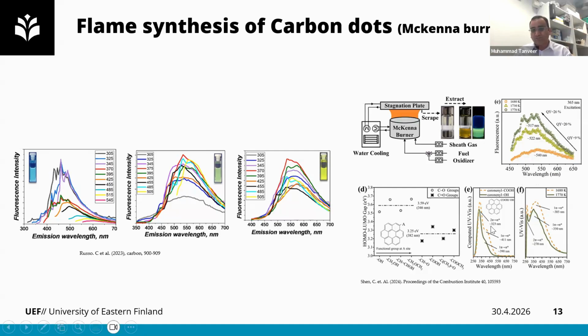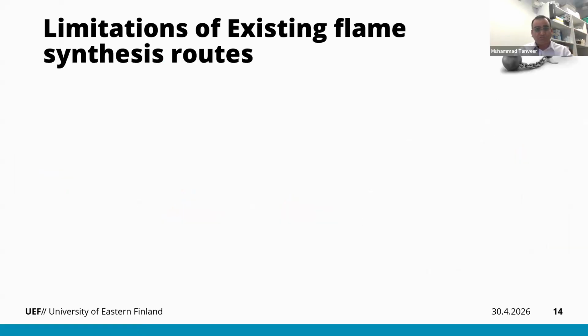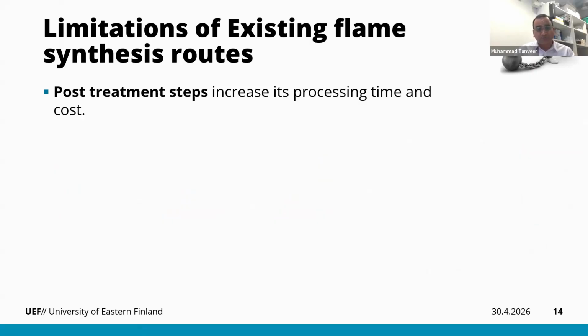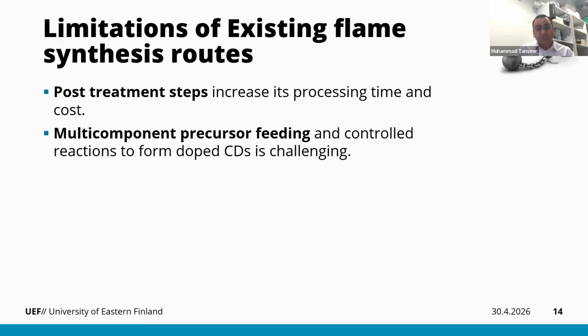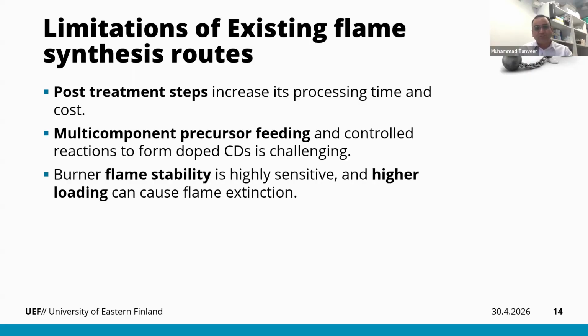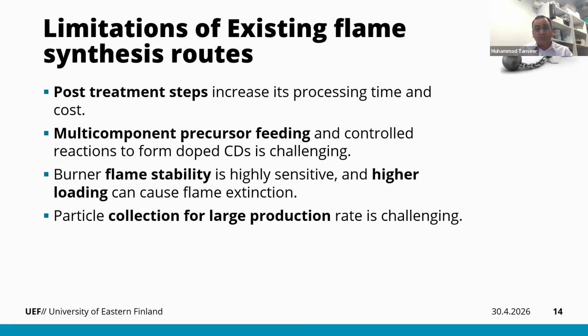Also, the pi transition and some chromophores on the surface of carbon dots play a role in defining the optical features of these nanostructures. Although these flame synthesis routes are quite effective, still there are some limitations, and there's still a gap to fill. Like these systems need post-treatment steps, which increase the cost and also time. They are difficult to handle multi-component precursor feeding. So if there is a multi-component reaction system, then it's difficult to control it. Like we cannot use this system to dope our CDs to further tune the properties of these nanostructures. Also, their flame stability is quite sensitive, and under higher loading, the flame can be extinguished. And then particle collection for large production scale rate is challenging.